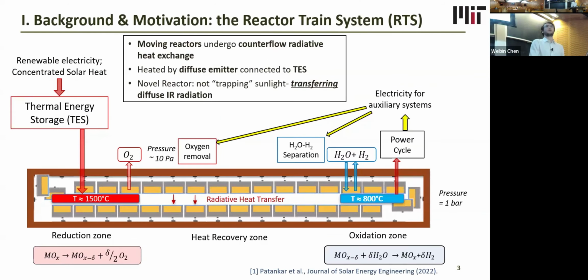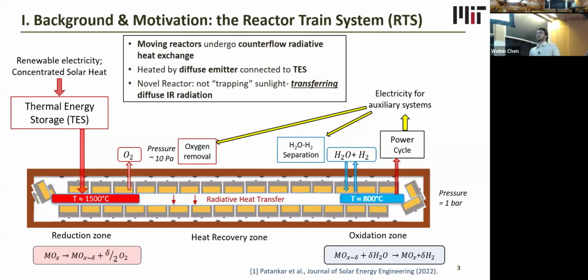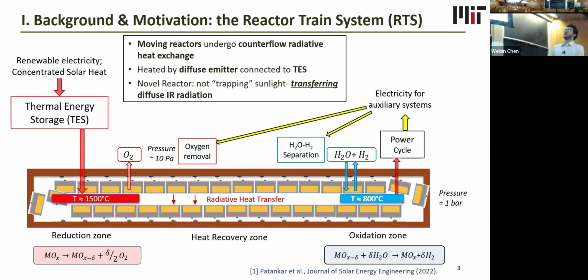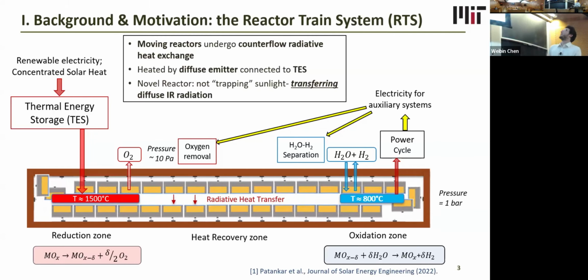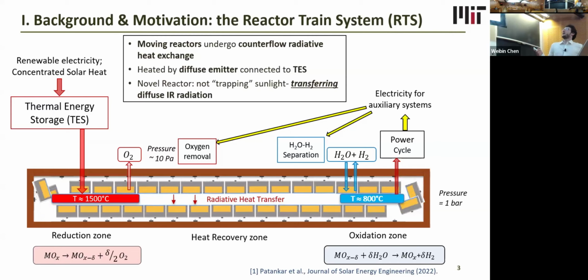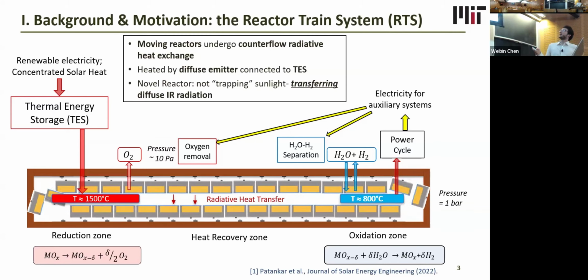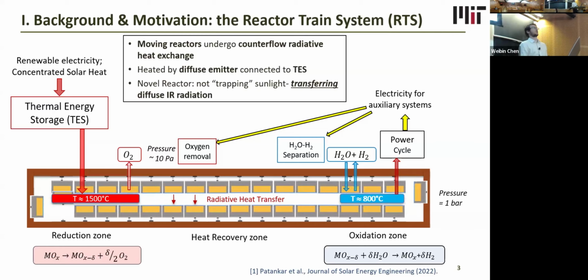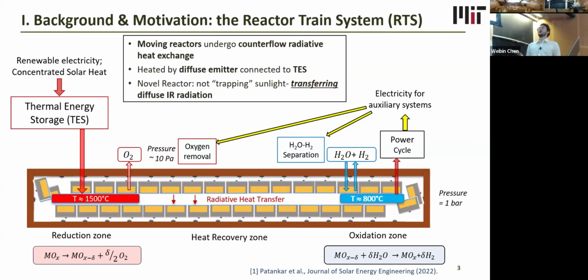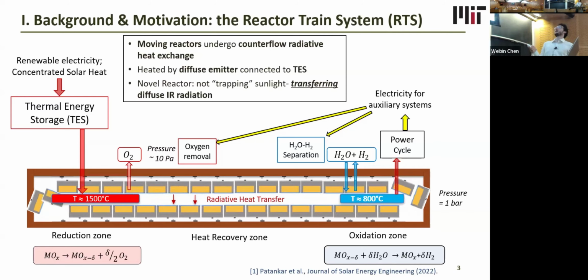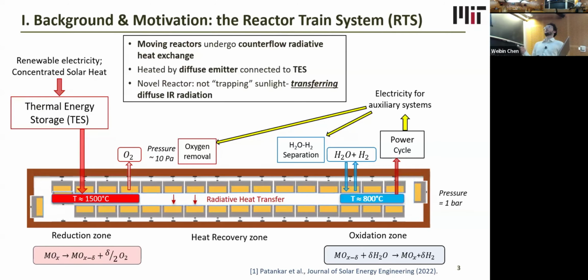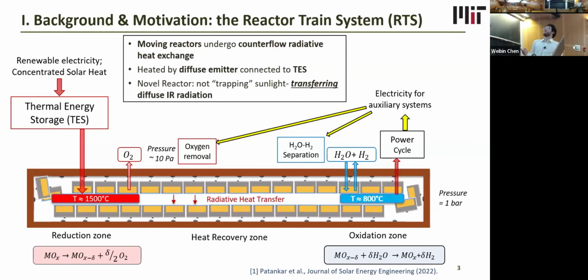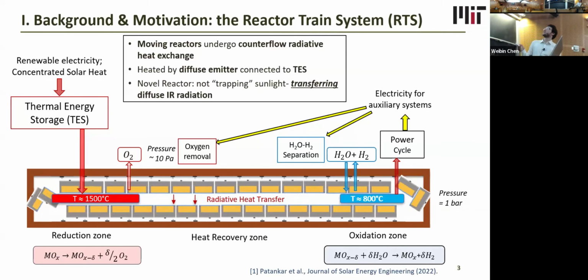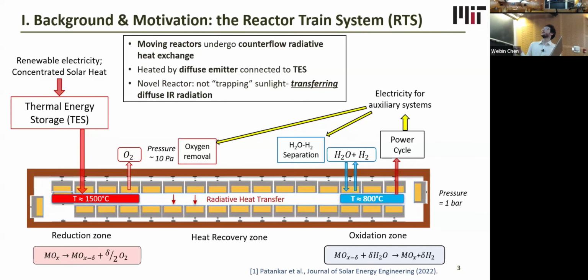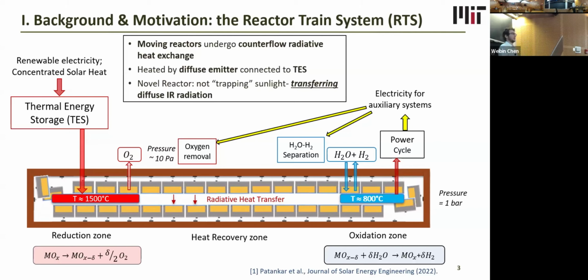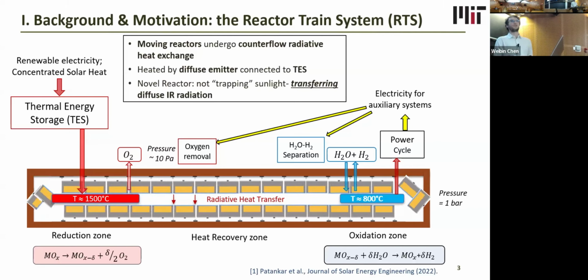To address this issue of heat recovery, a few years ago people in our lab came up with a concept called the reactor train system, and you can see an animation of it up here. In essence, these boxes all represent individual thermochemical reactors, which each contain a bit of redox material, metal oxide, and they're cycling continuously between a high temperature reduction zone and a lower temperature oxidation zone. The key innovation is that in between these two steps, they are engaging in counterflow radiative heat exchange, which could potentially lead to very high heat exchange efficiencies.